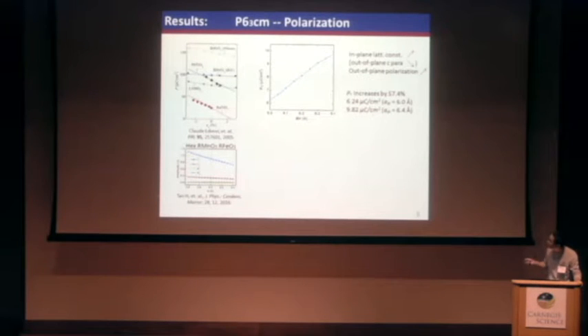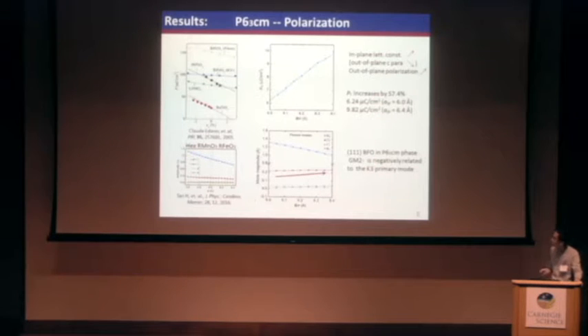So similarly to this kind of analysis, we also look at the modes, the phonon modes. When increasing the in-plane lattice constant, the primary K3 mode decreases, while the polar mode, the gamma-2 minus polar mode, increases. It's different from here. So yeah, this might be the direct reason for the increasing of the polarization.